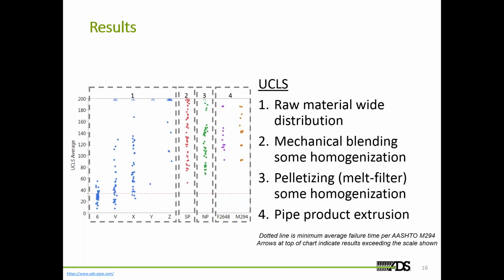Again, kind of a rather similar story when you're looking at NCLS or UCLS and those different raw material streams. That 6 material is the post-consumer recycled material. Then comparing that to the post-industrial flake films, you could tell it's kind of by and large a poor performing material. But as we move it through our raw material streams, that SP material at the bottom is basically a salt and pepper blended homogenized material. So again, that was material among all those raw material streams that was homogenized by mechanical means.